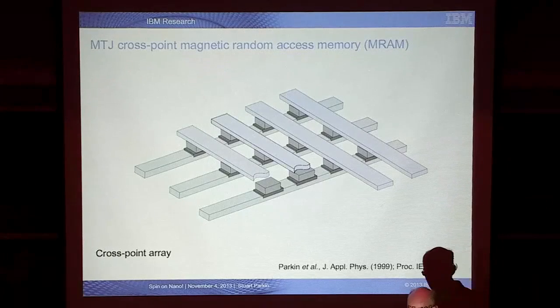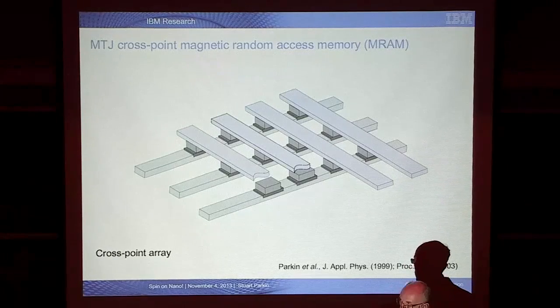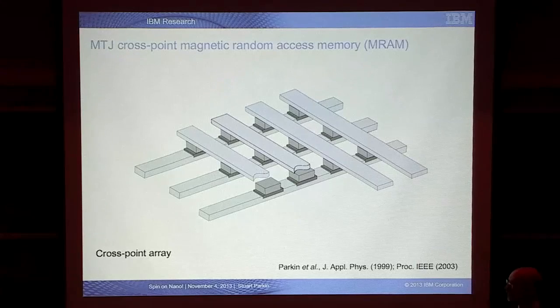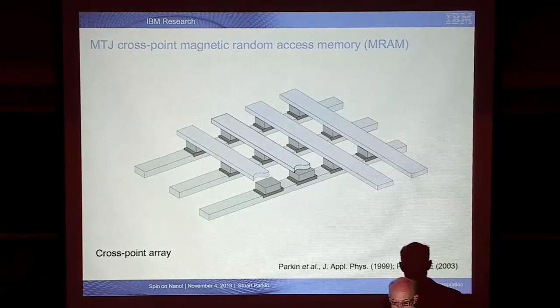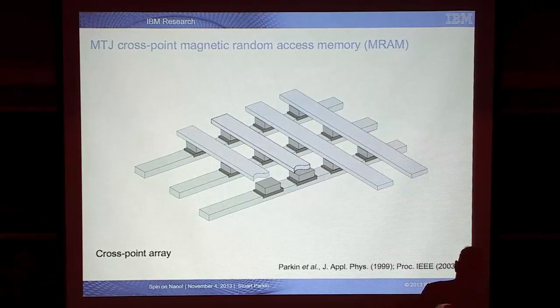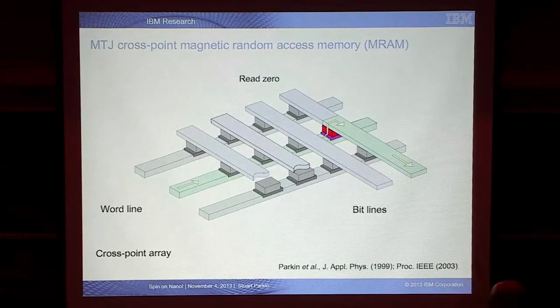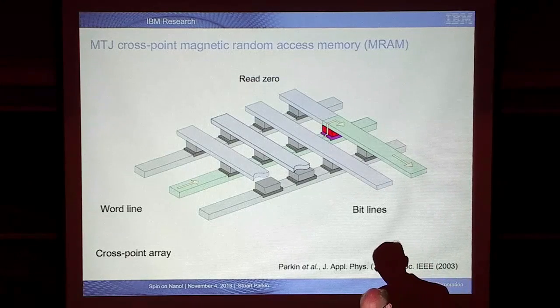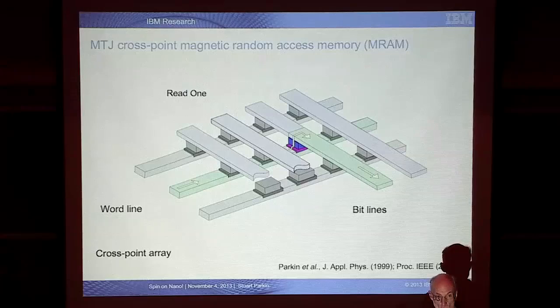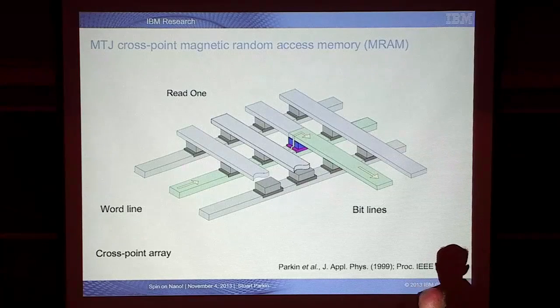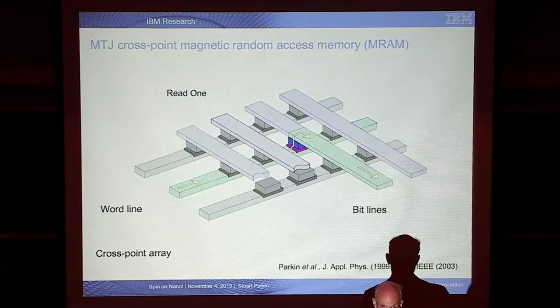We can insert this tunnel junction device because we can tune its resistance so that it gives just the resistance we need to detect its state by passing tiny currents. So if we pass a current along this word line and then exit the current through a particular bit line, we can detect the resistance of this magnetic tunnel junction state. And if the magnetic layers are parallel, we're going to detect a big current. If they're antiparallel, we're going to detect a small current. And in this way, we can read whether the state is a 0 or a 1.